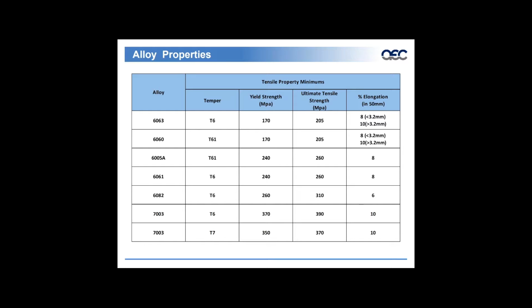When we look at the different alloys, this is an example of some of the specific alloys within the 6000 series. This is a broad spectrum, from the 6063, a lower magnesium silicon alloy, all the way up to a 6082, which is higher strength, and a 7003 in two different tempers. This represents the temper of that specific alloy, as well as the yield strength, ultimate strength, and percent elongation. These are minimum requirements relative to these alloys.